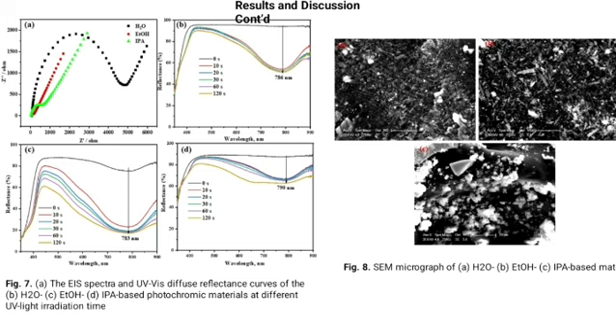For the morphological characterizations, the water-based material showed a surface morphology with uniform stripes that are embedded with unevenly dispersed spherical and cubic structures, while the ethanol-based material displays non-uniformly distributed and aggregated rod-like particles, as well as irregular shaped cubic particles in the isopropyl alcohol-based material. The observed differences in the surface morphology of the materials show that the different co-solvent solutions could differently influence the mobility of the electrons in the particles of the material,